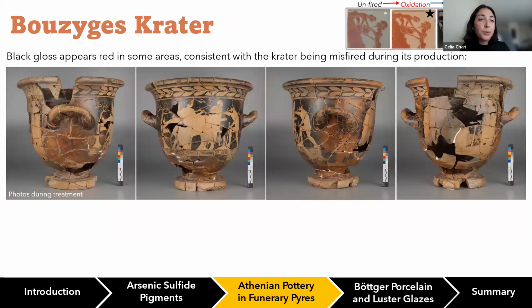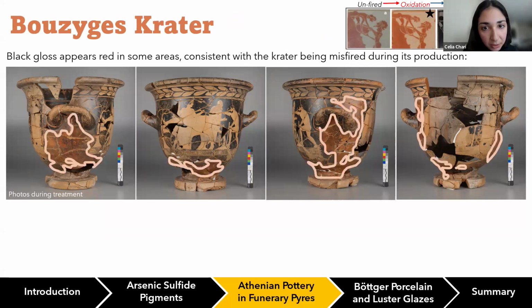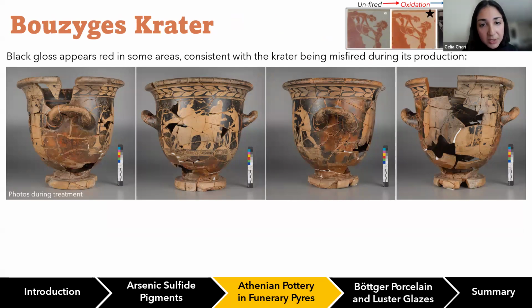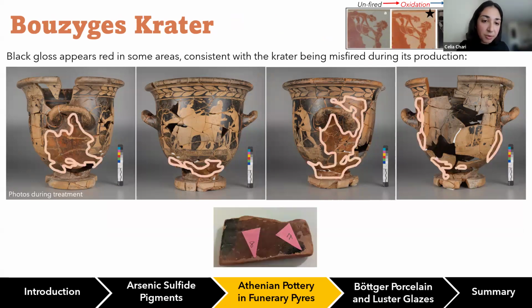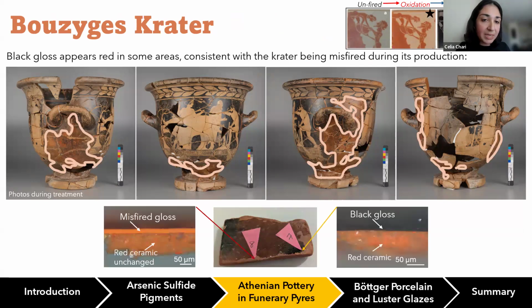In the case of the Bouzyges Krater, we started to notice some deviations to what we would typically expect from red figure. The first are these little regions here. So this red is in regions where we would expect to see black gloss.